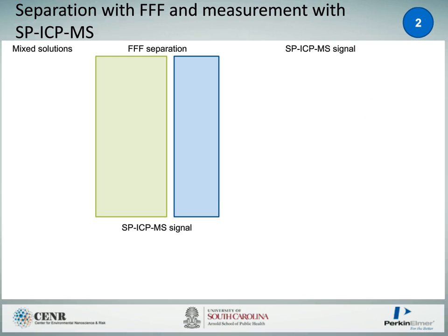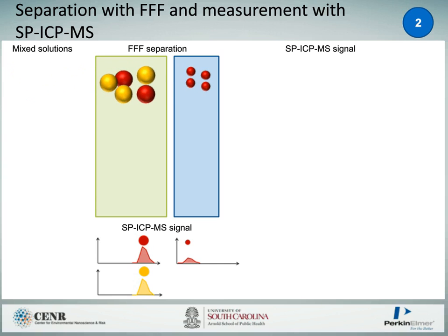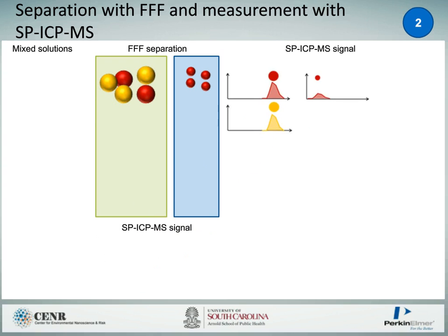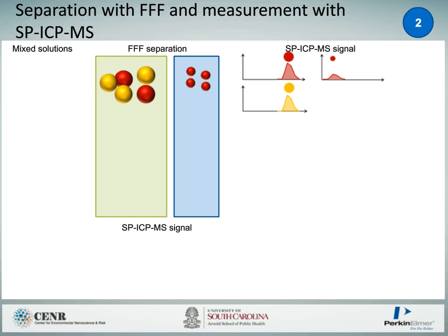So first of all, I'd like to talk about separation by FFF and measurements by ICP-MS. If we had a mixture of solutions that had monometallic particles, large and small, within it, if we put it through the FFF, it's going to separate, so the smaller particles will elute faster and the larger particles will elute later. If you collect these separate fractions and put them through the single-particle ICP-MS, we're going to get small particles for the first fraction and large particles for the later fraction, which will be synonymous with the size and diameter.